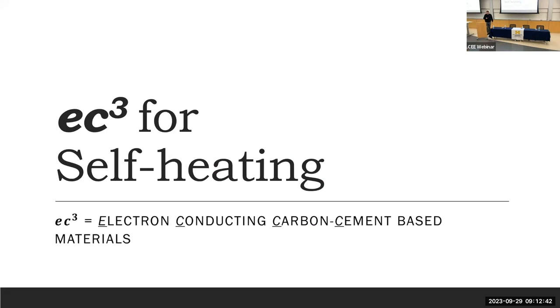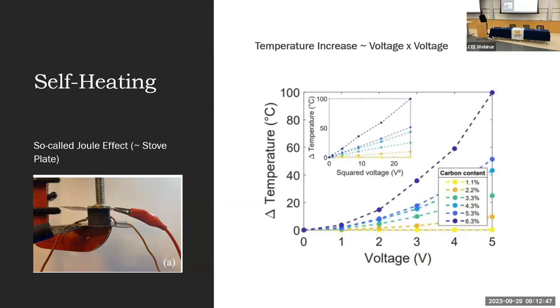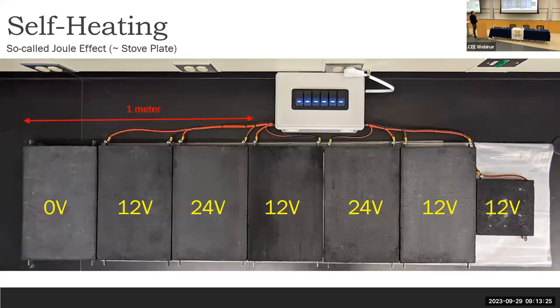Well, what can you do with this material? In fact, if you look here, if you put such a material between two conductive plates and then put a positive and a negative charge on two sides and measure the temperature, you actually see that as you increase the voltage, the temperature scales with the voltage to the power 2, which provides a highly accurate way of monitoring the energy, the so-called Joule effect, the heat release by means of just charging, like an electric stove, the material. That's a dissipative process which takes place at a relatively small scale. And you can scale this actually very neatly.